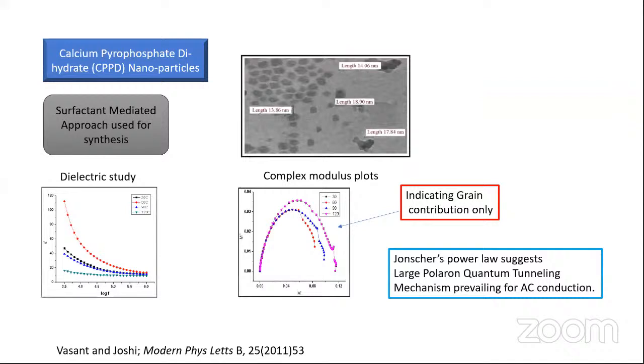For this particular purpose, we have concentrated in our lab on calcium pyrophosphate dihydrate nanoparticles, and we have synthesized the nanoparticles by a surfactant mediated approach. The TEM image shows the rod-like calcium pyrophosphate. Purposefully, I discuss here the dielectric properties. Other properties we have studied, but the dielectric properties are interesting because they have direct applications in bone healing.